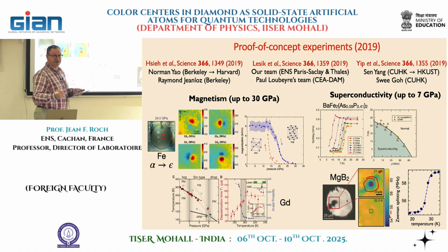And now if we increase the temperature, this expulsion will become weaker and weaker, up to a point where we now have a uniform distribution of the magnetic field experienced here. And from just measuring the Zeeman splitting on top of the sample, we have this curve, and we can determine from that the critical temperature Tc. This critical temperature is 30 Kelvin, as measured for this compound with other techniques. And that was done at a pressure of 7 gigapascal.